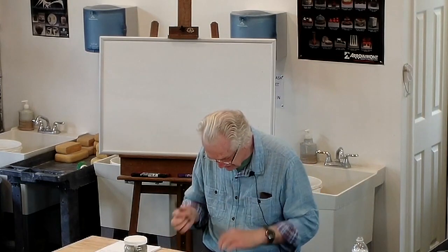And so, for instance, commercial underglazes, those are engobes. Actually, the fact that they contain a color doesn't matter. They contain a pigment and a little bit of flux, but they don't completely melt and turn into a glass, okay? So here's a dark engobe, and it's really easy. Just cone 10, local red clay, which could be your clay from your backyard, and some potash feldspar. Okay?